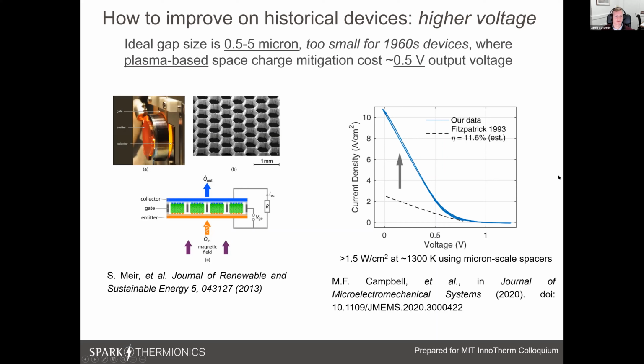And on the right side, you can see some of our data. This shows that for the first time, we can actually get power densities that are of relevance for thermionic devices. Fitzpatrick in 1993 achieved a 10 micron gap, which is fairly good enough in order to get a reasonable current out. And what you can see is at a very low temperature from a historical thermionic perspective of about 1300 Kelvin, or just above 1000 Celsius, we're able to achieve with micron gap spacers over a watt per square centimeter, which, as I'll refer to later, is a very important threshold. And I'll remind you again that this was just with conventional thermionic materials. Both emitter and collector in this case were just molybdenum with a low work function coating.